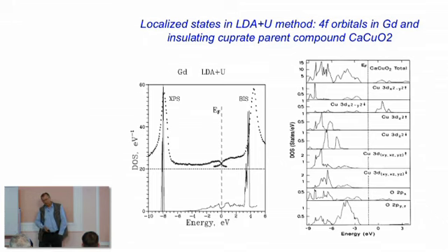So this is the parent, which means that it's experimentally an antiferromagnetic insulator, but standard density functional will give you a non-magnetic metal, while LDA+U immediately gives the correct ground state. Here, you see that only unoccupied and occupied D states are shifted, unoccupied up in energy, occupied below, and that stabilizes the insulator. So the LDA+U correction stabilizes the insulating solution, and the antiferromagnetic one as well.